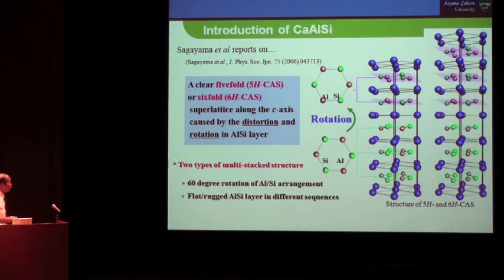The idea is very simple. Calcium silicon 2 is a superconductor under high pressure, so Imai-san tried to shrink the silicon layer and substitute 50% aluminum at the silicon site.